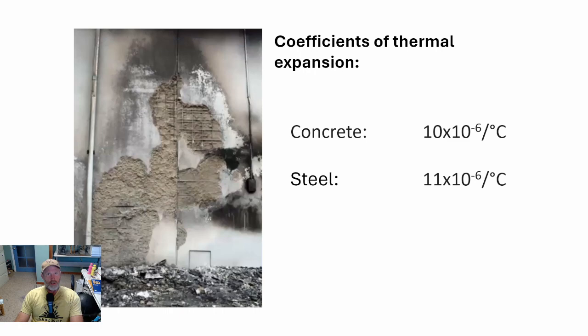People have erroneously assumed that spalling is due to a difference in thermal expansion coefficients between steel and concrete. As you can see, the difference between those thermal expansions is roughly 10%. But steel has a conductivity 50 plus times more than concrete, meaning the steel is effectively going to be the temperature of the concrete. That 10% difference really doesn't make a lot of difference in spalling because of the compressible nature of steel. So the primary mechanisms for spalling are the temperature gradient in the concrete itself, resulting in differences in expansion, as well as the explosive nature of steam generated within the concrete.